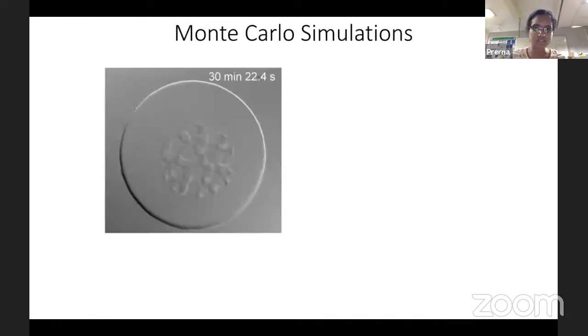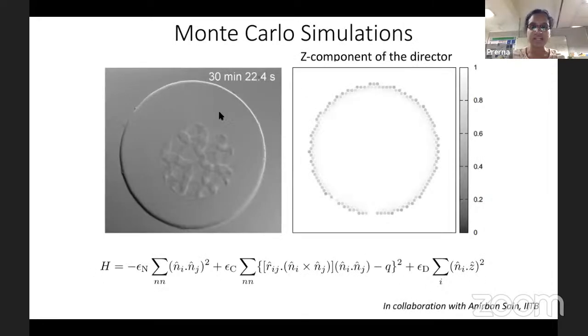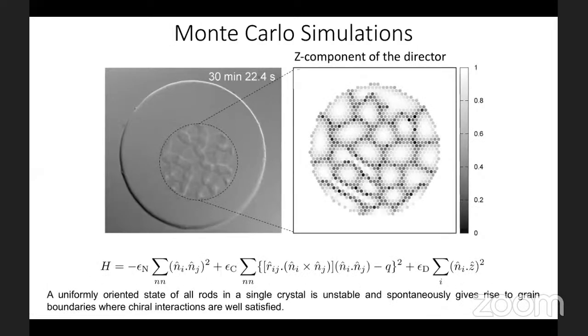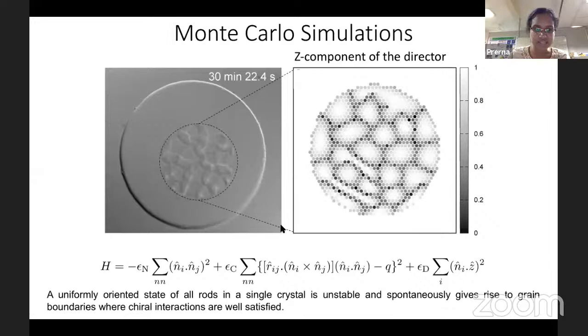So what is really going on? What is really going on is the following: by crystallizing these chiral rods, you have really suppressed their chiral interactions. This is a 2D simulation where white means all the rods are aligned, and 0 means the rods have a finite angle. If you evolve this kind of configuration under an energy Hamiltonian, which depends on the chirality, you will find that it becomes spontaneously unstable. What I'm really trying to say is that a uniformly oriented state of all rods is unstable and will spontaneously form these grain boundaries where the chiral interactions are satisfied. So a single crystal of aligned rods becomes unstable to the formation of grain boundaries where chiral interactions can be satisfied. This is the crux of the story.